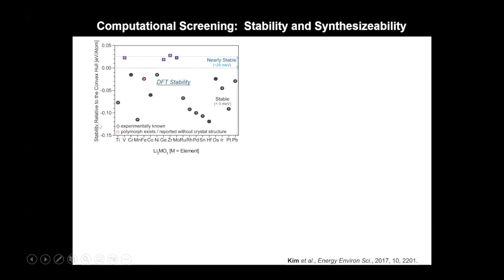The y-axis of this plot is essentially a measure of the thermodynamic stability of the compound. It's a measure of whether or not this compound is on the lowest energy envelope, which we call the convex hull. In this plot, a negative value means that the compound is calculated via DFT to be thermodynamically stable on the convex hull. A positive value means it's above the convex hull, which technically means it's unstable. There's something lower in energy on the convex hull.